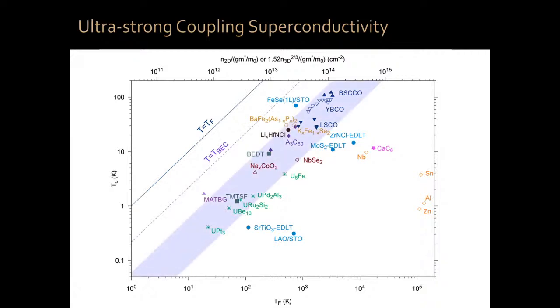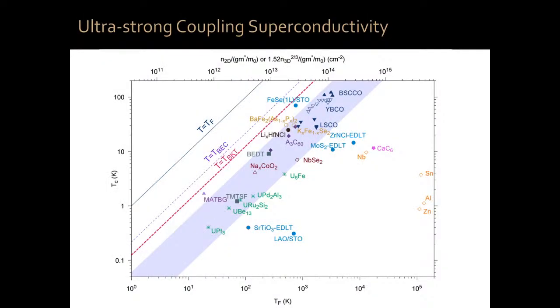In this plot, I'm going to put a few lines here. In this plot, conventional superconductors, such as aluminum, tend to be near this corner, okay? So for example, aluminum has a Tc of about 1 Kelvin and a Fermi temperature of over 100,000 Kelvin. Given the gigantic density of electrons that aluminum has, it superconducts relatively modestly, okay? As you go towards this purple band here, diagonally in that direction, you have more and more exotic types of superconductors. In fact, in that purple band, we have all of the unconventional superconductors that we know. We have the cuprates, the heavy fermions, the pnictides, the organics, they're all here.